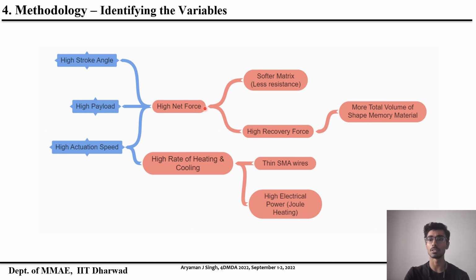For higher net force, the matrix should be soft and flexible so that it doesn't resist the recovery force, and high quantity of shape memory material will result in high recovery force. So, the higher the amount of SMA wires, the more force will be produced. For high rates of heating and cooling, we propose to use thin SMA wires, and using high electrical power will also increase the joule heating rate.